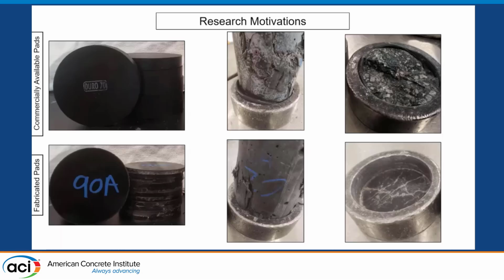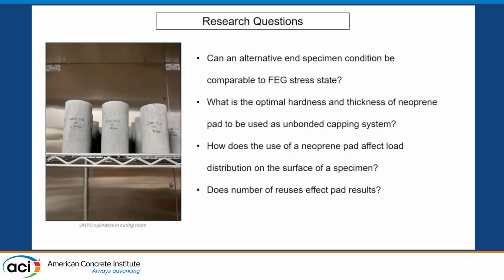So in the center top photo, you can see evidence of confinement. And the pad is essentially destroyed after testing. So he thought, let's use a harder pad. On the bottom, you can see a fabricated 90A pad, and there's no evidence of confinement, and the pad is still intact after testing.